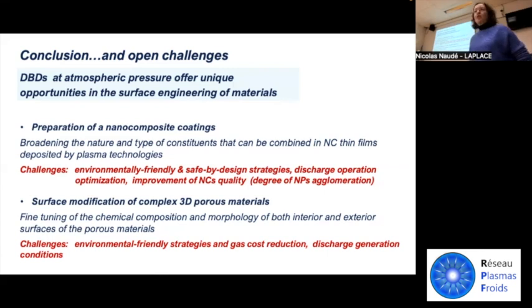To be honest, there are some conditions in which there is such evolution. But since we inject a high amount of dispersion and we use a pulsed mode, we tried to have, at the center, where the length of our electrode is 5 centimeters, the 2 centimeters in the middle, a uniform composition. In that case, we did not observe gradients, but really because we tried to focus on a condition in which we could obtain uniformity, also for the foam.